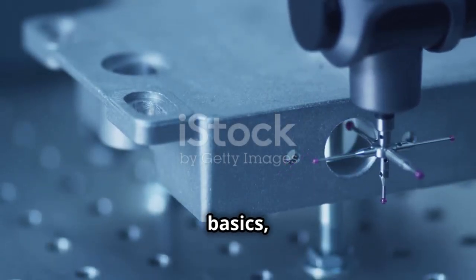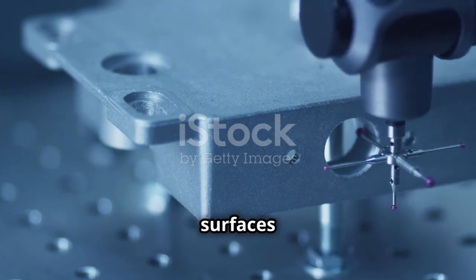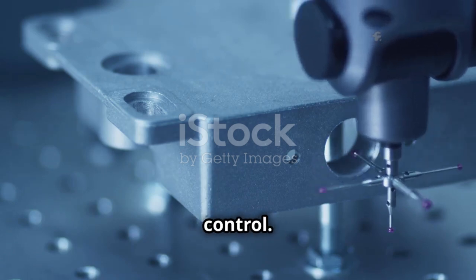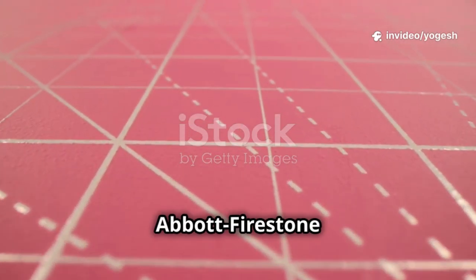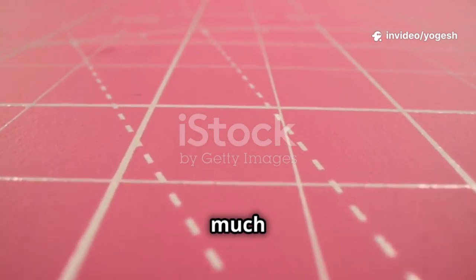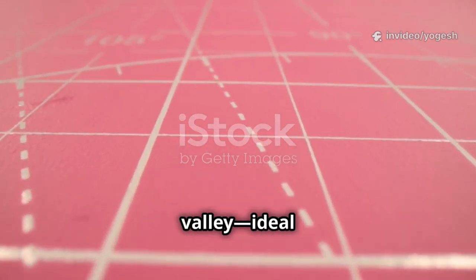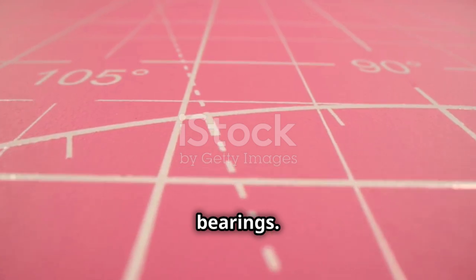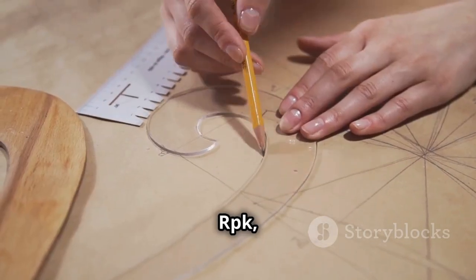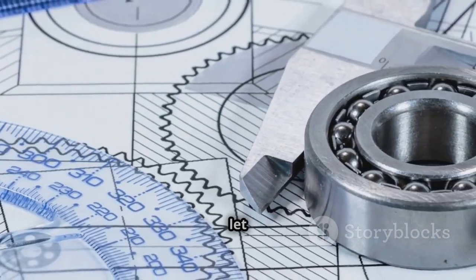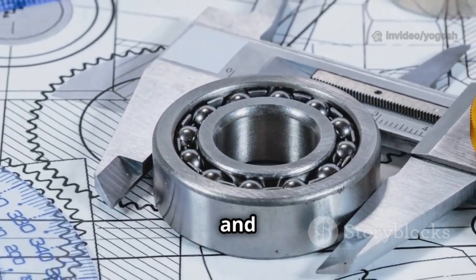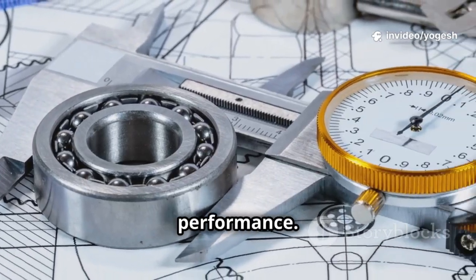Once you've mastered the basics, you can fine-tune surfaces for even greater control. Profile tolerancing uses the Abbott-Firestone curve to define how much of the surface is plateau versus valley, ideal for bearings. Parameters like Rpk, Rk, and Rvk let you specify peak, core, and valley depths for targeted performance.